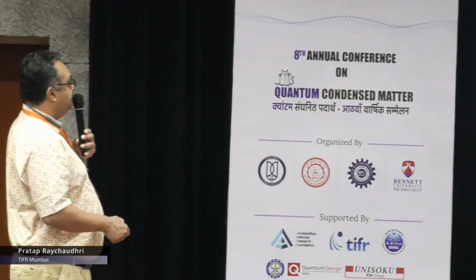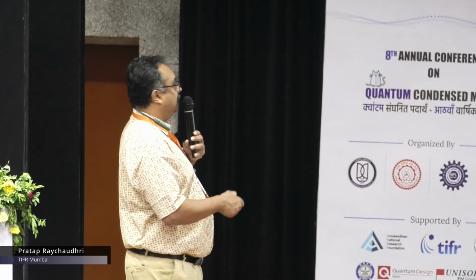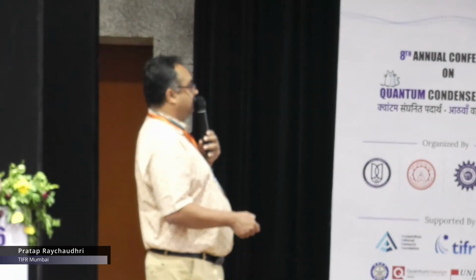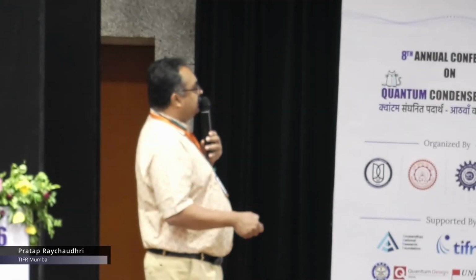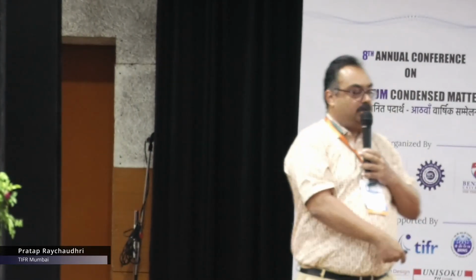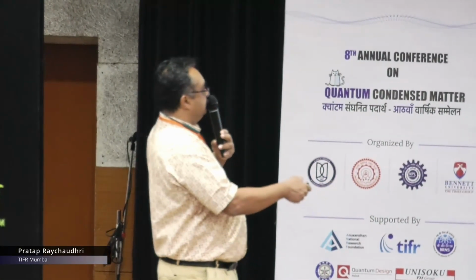And this was actually verified when we do resistance as a function of magnetic field at 300 millikelvin, we see nothing. But then when we do this measurement, we always avoid electromagnetic radiations from outside to get into my sample. So we put filters.